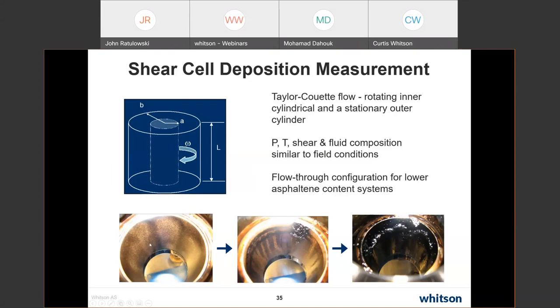And this is just a series of pictures of the cell opened up after a period of time, with the same fluid. So this is early time where we get kind of this adsorbed layer on the entire surface. And then we see kind of growth of larger macroscopic deposits over time as we go to longer times. And this is not really very uniform. It's not like the wax deposits.